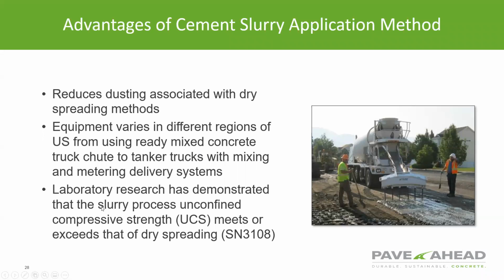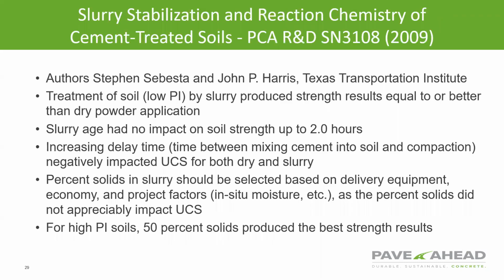Laboratory has demonstrated that there really is not much difference at all between the slurry process and that of a dry spreading process as far as the unconfined compressive strength. So as far as performance between the slurry method and the dry method, there's really no measurable difference between those two.